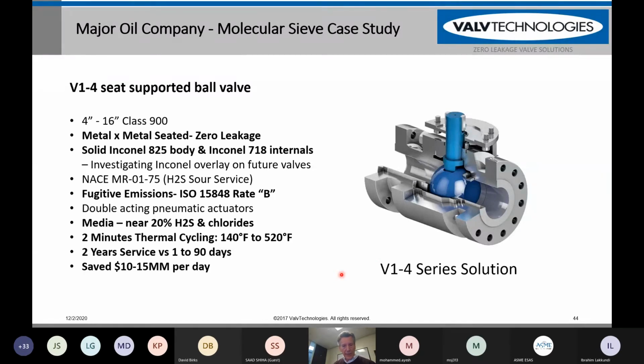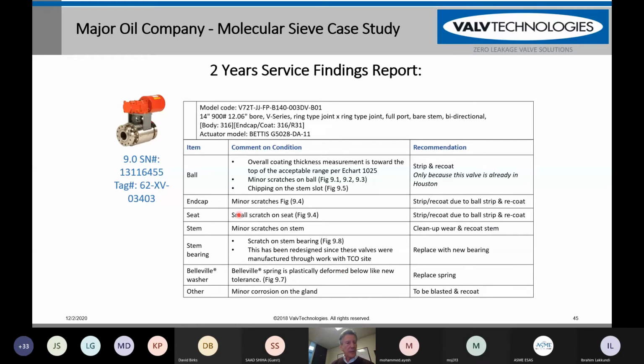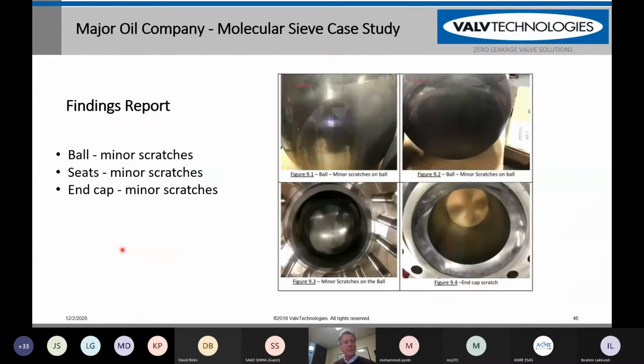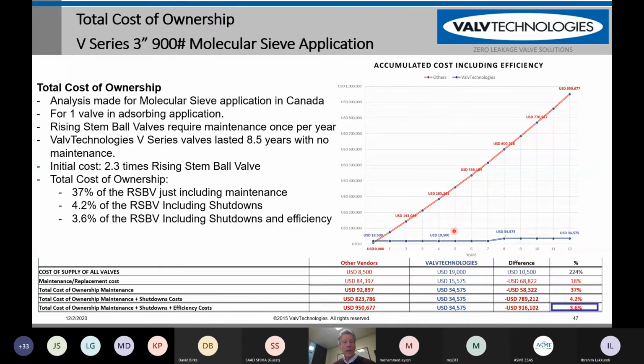The valves were taken out of cycle and sent back to the factory, where our customer came to our factory. This is the finding, an excerpt from our joint case study that we did with our end user. This is the actual valve with the serial number and tag number. After disassembly of the valve, we saw that although there was slight discoloration because of the high temperature swings, there's no damage or delamination of the tungsten carbide on the seats or the ball. The valve was still working perfectly well.